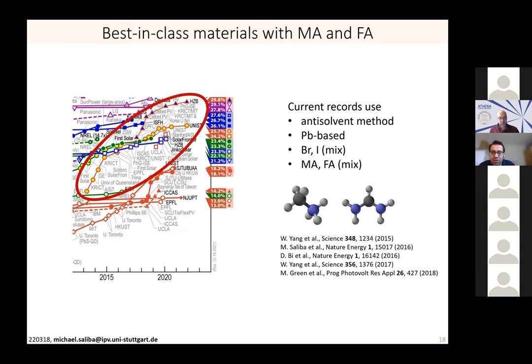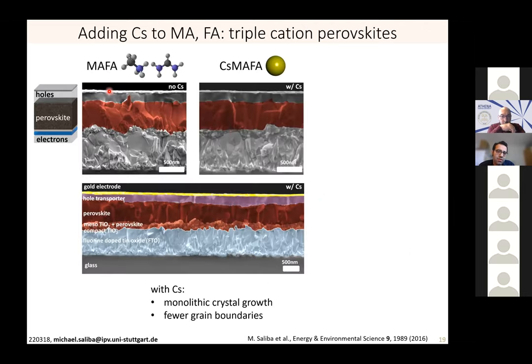And you can see how all of these materials use lead, anti-solvent, and methylammonium formamidinium mixtures most of the time. So one thing we started looking at was what would happen if we use the most efficient material at the time, methylammonium and formamidinium, so a double cation perovskite. How does it look in terms of its cross-sectional SEM here? And what happens if we add a small component of cesium to form a triple cation perovskite?